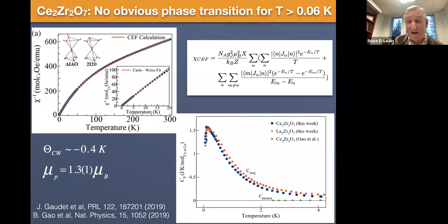There is a Schottky anomaly, which is here at about 100 millikelvin or maybe 80 millikelvin. There's a peak, and then the heat capacity falls off, as it has to go to zero at T equals 0, and it falls off quite abruptly. And we're going to be analyzing the high temperature part of this heat capacity later on. But at any rate, from this, we could see that the Curie-Weiss constant was about minus half a Kelvin, and the paramagnetic moment was relatively small, as expected, about 1.3 μB, and so forth.